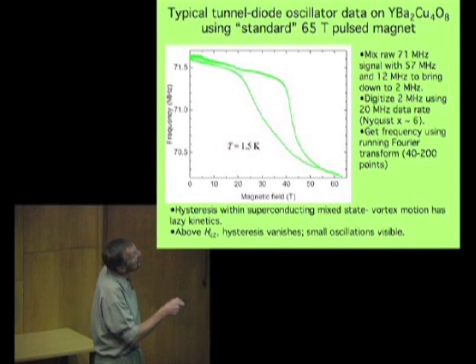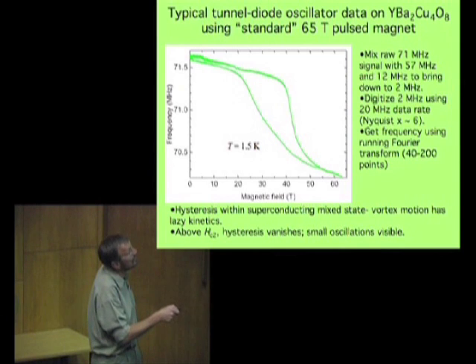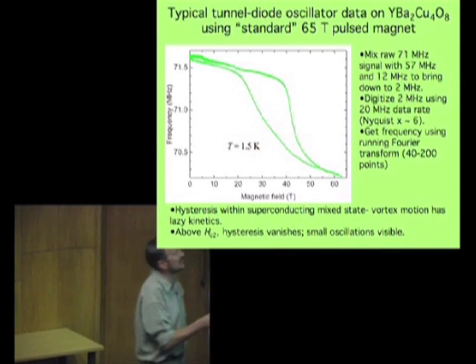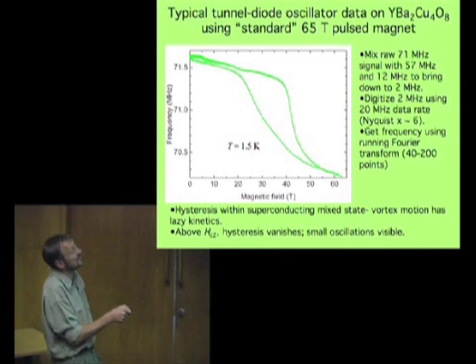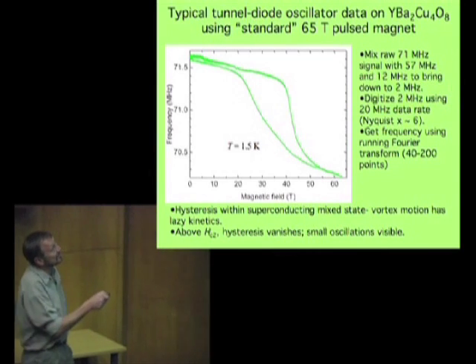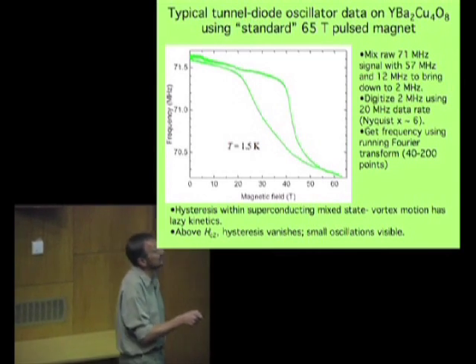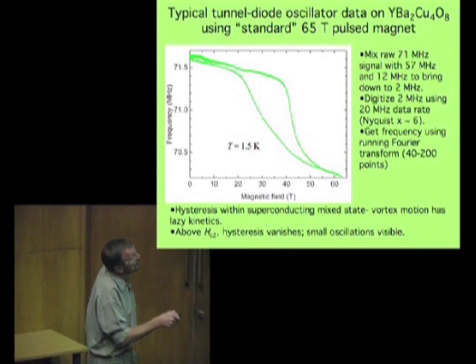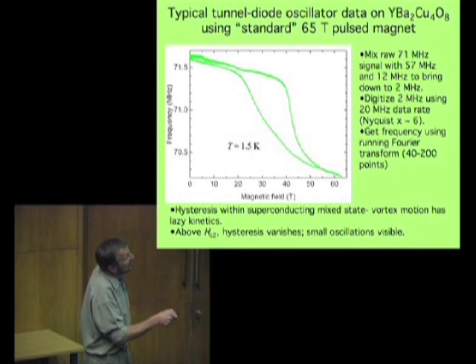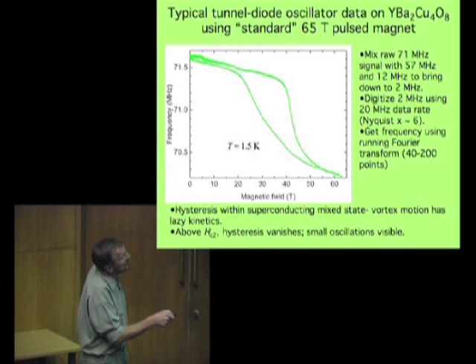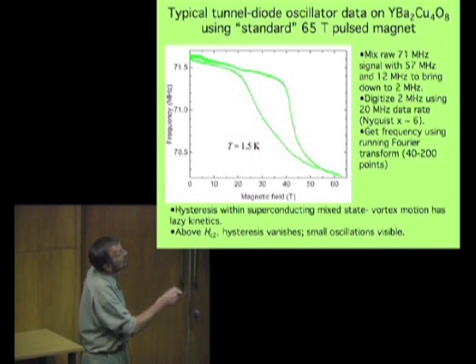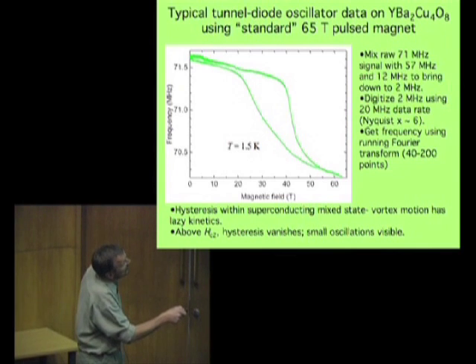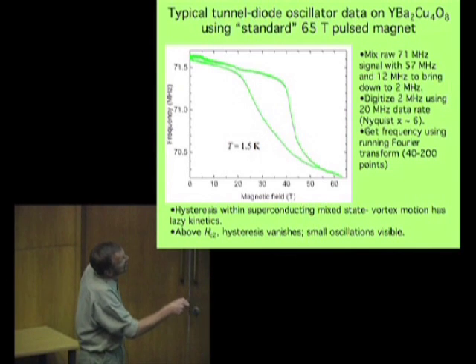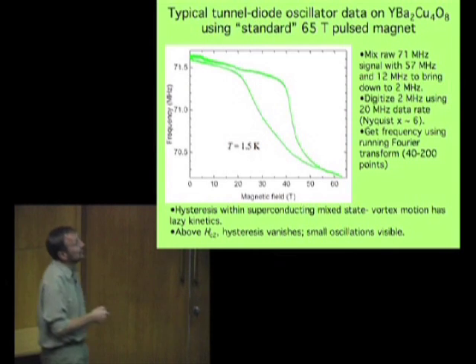So on the upsweep, basically you get a lot of slow exit of vortices from the sample, slow entrance of vortices to the sample, and a lot of heating caused as a result of that. Here, the sample finally stops doing that. It stabilizes its temperature. On the downsweep it's at the same temperature, and then here it's at a lower temperature than it was on the upsweep. So we have up, relatively hot, temperature stabilizes, down, looking relatively cold.